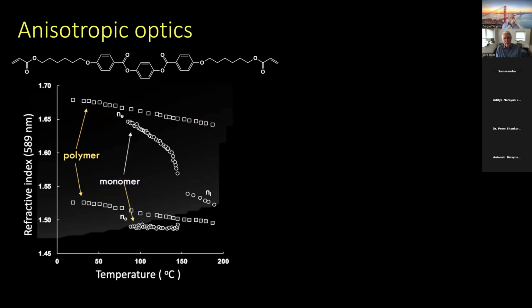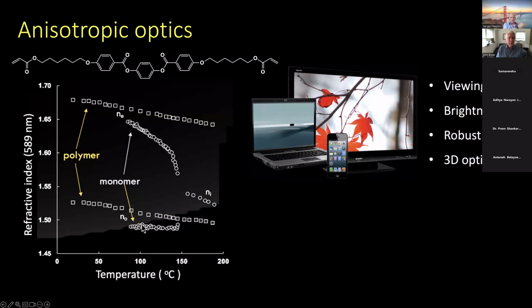But then, because we had this process in hands, we could actually make use of other properties of the material, and the property that was most interesting at that time were the anisotropic properties. Just like normal low molecular weight liquid crystals, they are anisotropic in their properties. They have a low ordinary refractive index and a high extraordinary index. This is the index parallel to the director of the system, the orientation direction of the system. This is the index measured perpendicular to that. This is just the behavior of the monomer in the monomer stage, just behaving like normal liquid crystals, so high difference, high birefringence, and when you heat it above the clearing temperature, when materials become isotropic, you end up with one isotropic index.